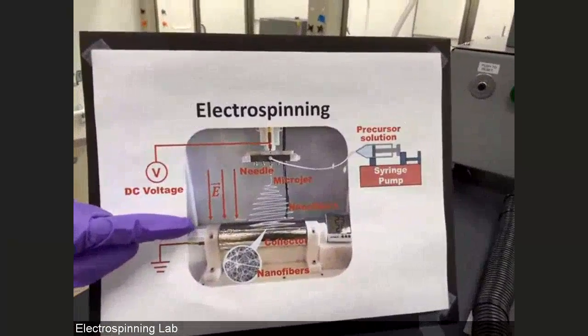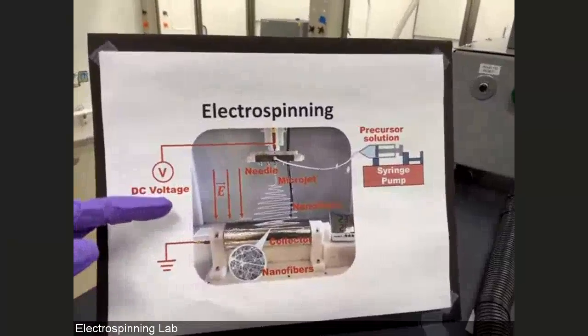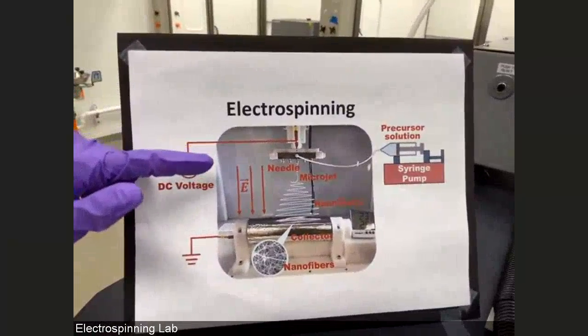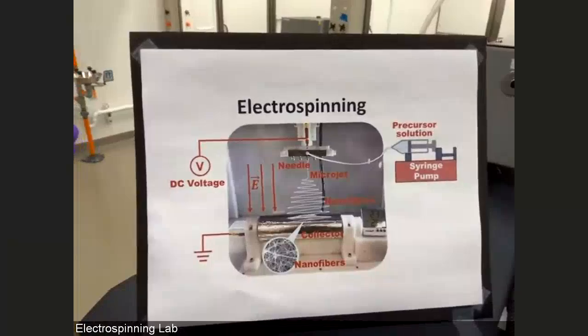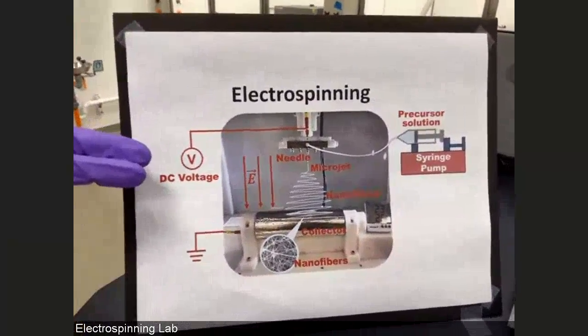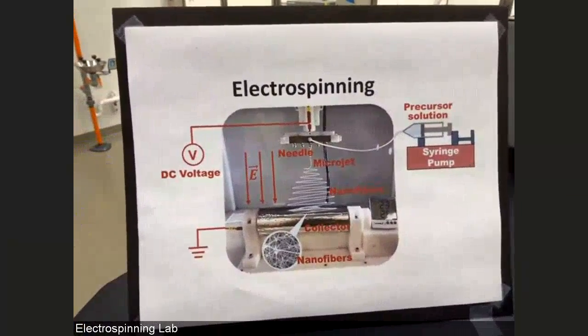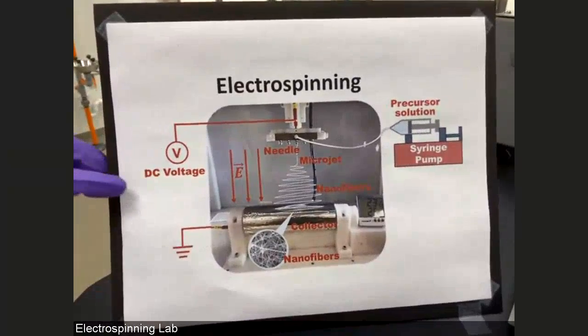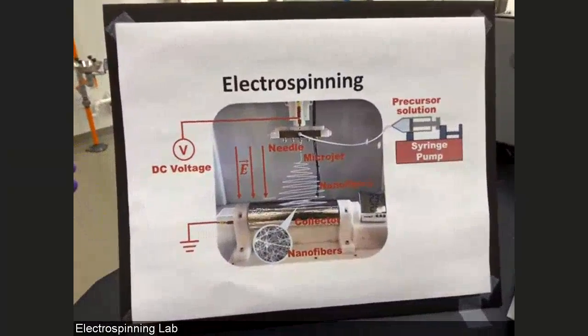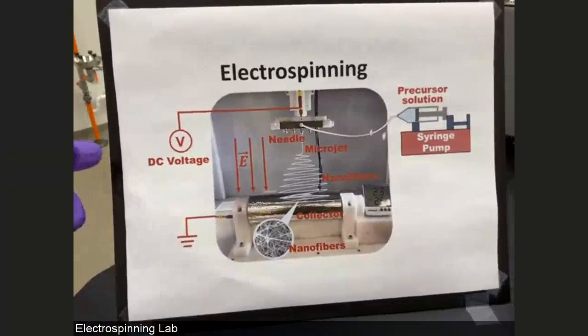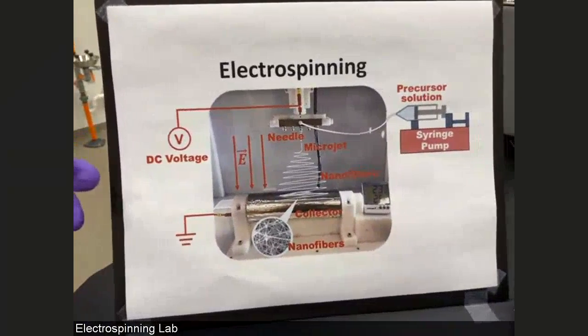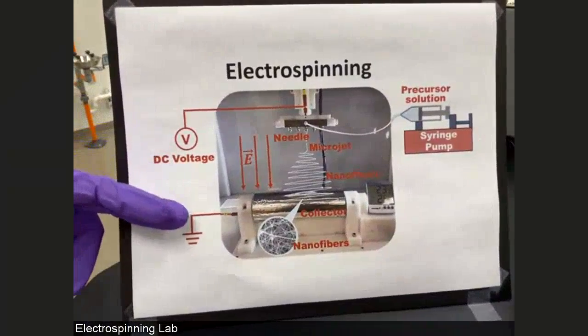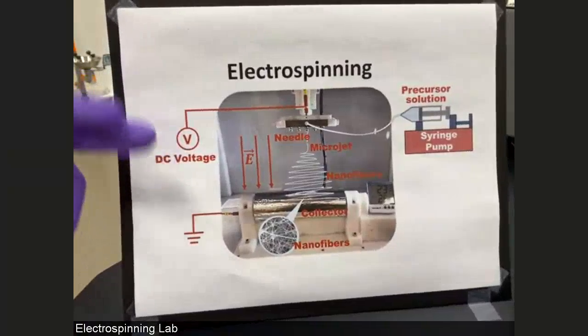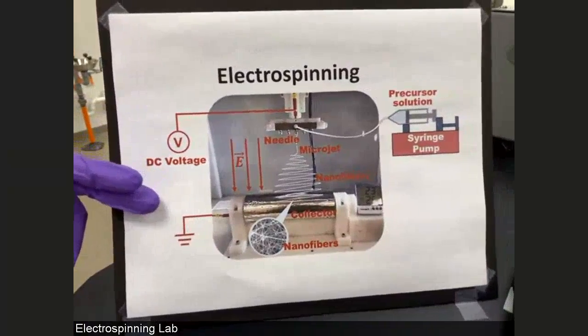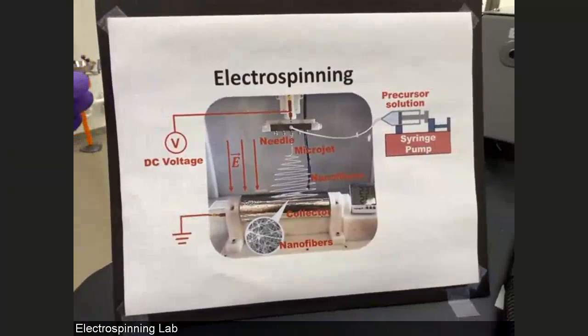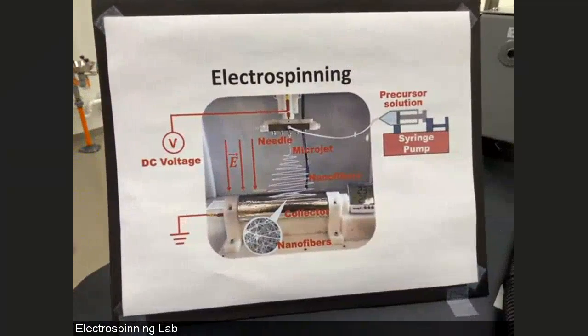And this electric field surpasses the surface tension of your polymer solution at the needle tip, and pulls the liquid out of the needle to form an elongated droplet called a Taylor cone. Now if your voltage is beyond a critical voltage, then you will form a microjet from the Taylor cone. This microjet travels towards the collector in the electric field. The liquid is charged, the solvent evaporates during this process, and you collect the dry fibers.